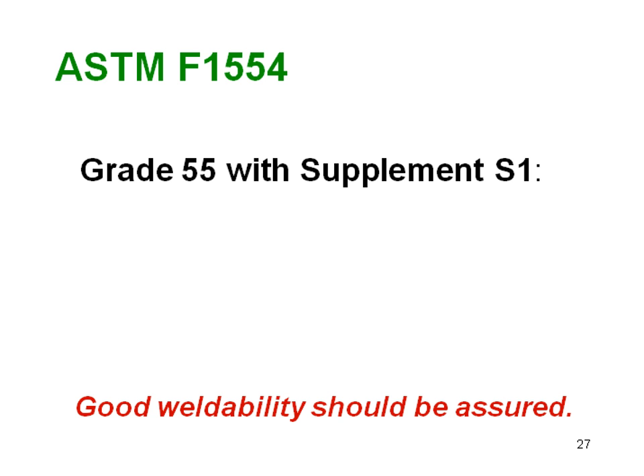To comply with supplement S1 are chemical requirements, and the rod could be analyzed by a materials lab, get your chemistry, get your alloys. You could see if it does or doesn't comply with those limits of the specification. And then there are the carbon equivalency equations. They're listed in the ASTM specification. You could make that calculation. And by making those checks, you could find out if that material that was not ordered in conformance with the supplement S1 actually, in fact, did comply with supplement S1 requirements.